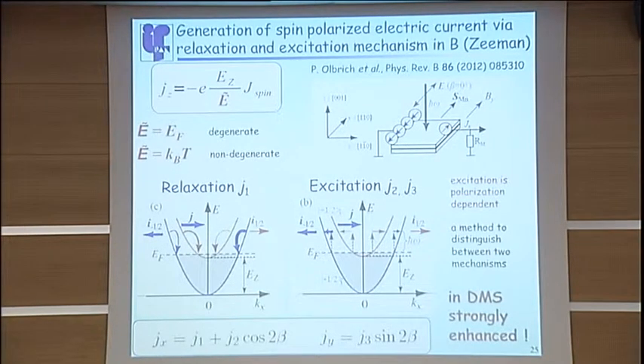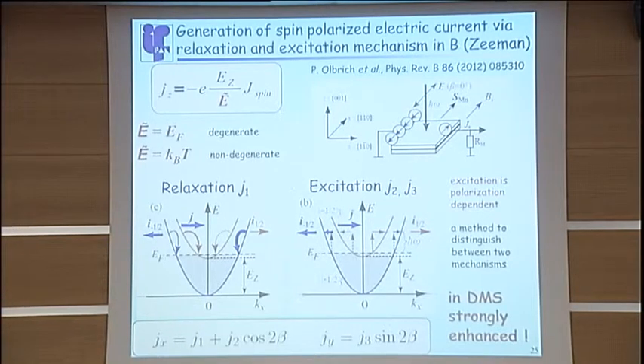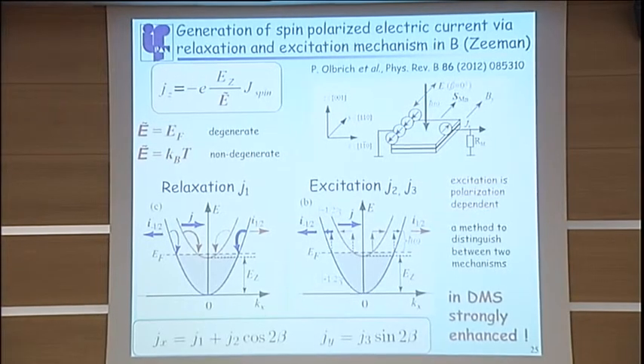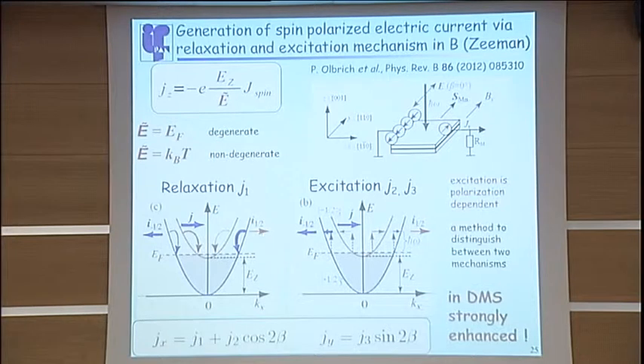And this can take place at the excitation level, and in this case, this excitation is polarization dependent, given by this formula. You measure the current in the configuration where the magnetic field is in plane, and you rotate the polarization of your light, and then, through absorption plus spin-dependent scattering. Now, also, if you already have these carriers at high energy, they relax to lower energy, and so you can have this generation of spin-polarized current at the stage of relaxation, and the total current should be given by this formula. And so at low spin splitting, the electrical current should scale with the Zeeman splitting.